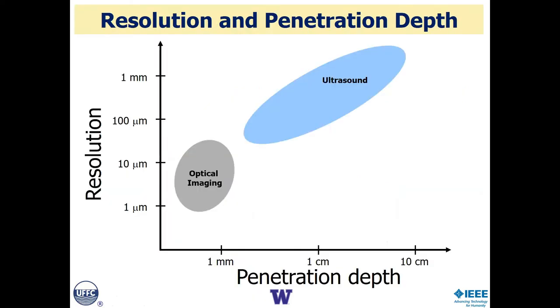Now, what this does is allows us to bridge two worlds. This is a simple biomedical imagers plot, which shows the resolution of the imaging system versus the penetration depth into the body. We have two well-developed fields: optical imaging, which creates micron to submicron resolution, but a penetration depth on the order of a millimeter, versus ultrasound, which can have penetration depths of 10 centimeters and more, tens of centimeters into the body, but at resolutions which are millimeter down to around 100 micron or so. What photoacoustics does is it allows us to span these two worlds.